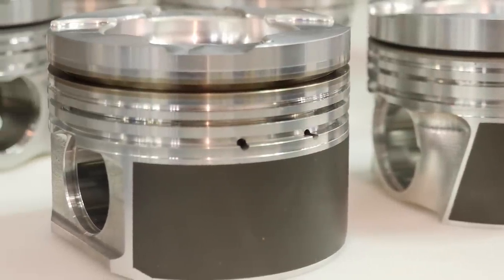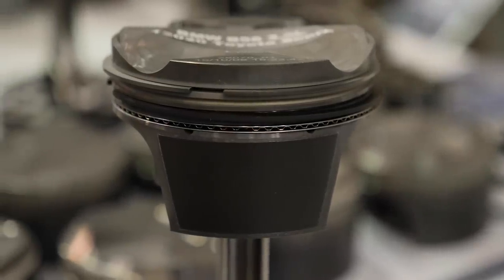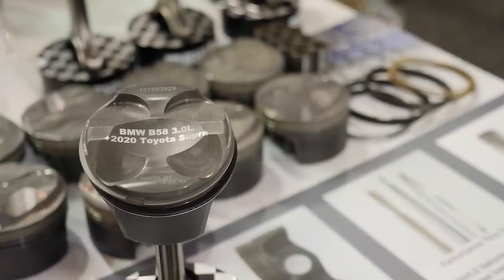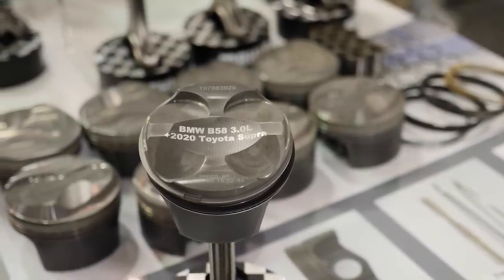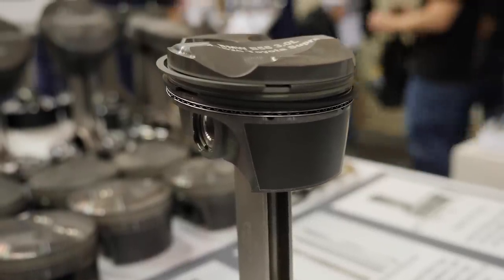Mahle's skirt coating is the friction reduction type, meant to be there for the life of the piston. It's the same coating used for OEM manufacturers, top race series pistons, and everyday shelf stock catalogue pistons — exact same formulation, exact same process. If everything is perfect in that engine, it'll be there as long as that piston lasts. The caveat is that perfection is very difficult to achieve, and when it's not perfect, the coating becomes sacrificial — taking the brunt of an overheated or marginally lubricated situation rather than scuffing the piston immediately, buying that extra margin of safety.